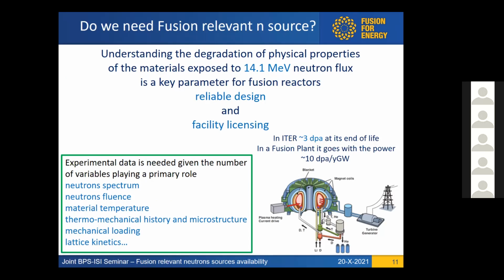We have neutron spectrums, which is a variable that is impacting a lot. Neutron fluence, temperature, thermomechanical history and microstructure of the material, mechanical loading, lattice kinetics. And you need to say, in ITER, you don't have a problem? No, because in ITER, we will only be having 3 dPa at the end of the machine lifetime. But in a fusion power plant, we will have above 10 dPa. About 10 dPa per year per gigawatt. We still don't know how DEMO will be. We talk about 1.5, 1.8, 2. Initially, we talked about 3.